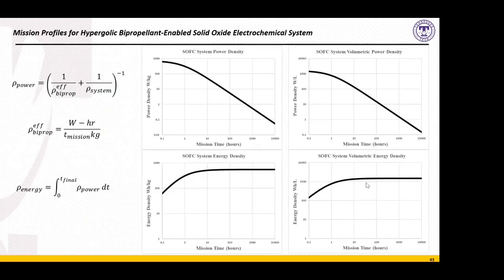By looking at a total system and its associated weight, and the power density of a stack and the effective energy density of the fuel given the efficiency of the stack, we can calculate the power density and the energy density as a function of the mission duration for the spacecraft. You see here the functions on the left-hand side. The effective power density of the bipropellant is going to again be that watt-hour per kilogram figure divided by the mission duration in hours or whatever the increment might be.